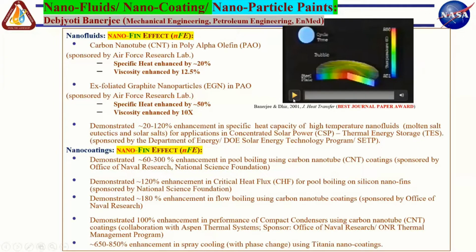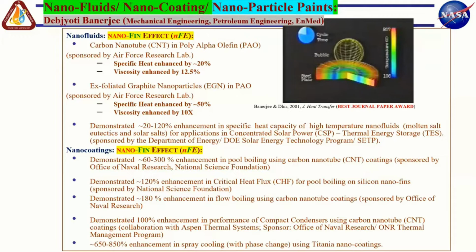But to our surprise, we found that the heat capacity went up as well. But that was not supposed to happen, because polyalpha olefin typically has a heat capacity of 2 joules per gram Kelvin. Nanoparticles typically are about 1 joule per gram Kelvin or less. So if you mix 1 and 2 together, you don't expect the number to be 2.1 on an average basis. You would expect it to be somewhere between 1 and 2.